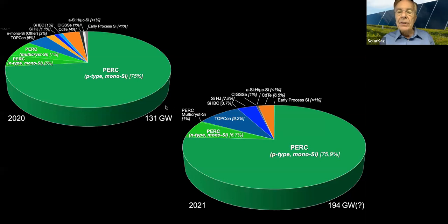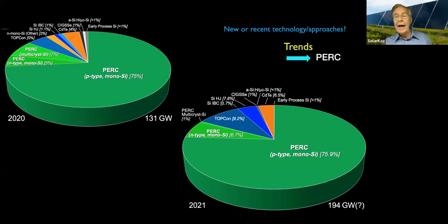The other thing that I am struck by is that the silicon heterojunction is also growing. This is that solar cell that has amorphous silicon on top of a crystalline silicon network. And the trends for these new technologies are, the trend toward PERC has been, and is still there, but on the silicon side it has also gone toward the use of single crystal, monocrystalline silicon, not so much multicrystalline or polycrystalline silicon anymore. And the trend is toward now the TOPCon cell. So you can see things changing, and the TOPCon one is an example of that.